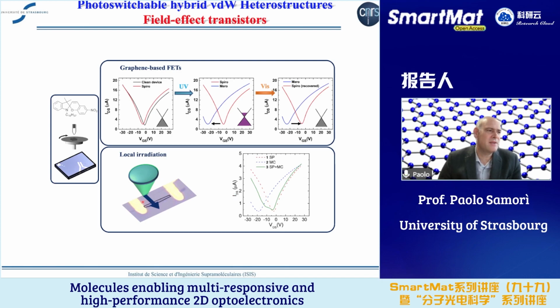And the way to do that is that you take a large crystal in the channel, a large graphene crystal, you spin coat the spiropyran on the top, and you irradiate the whole crystal with green light. And so you bring all the molecules into the merocyanine form, the blue one. And then you locally irradiate only a small part of the crystal with visible green light.